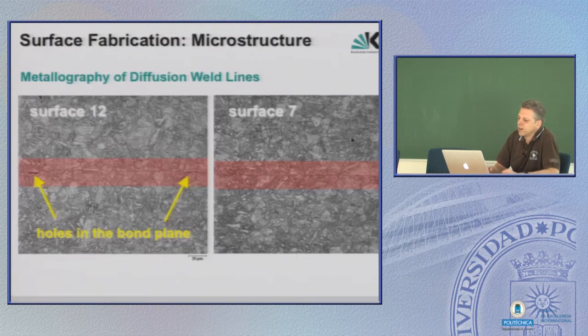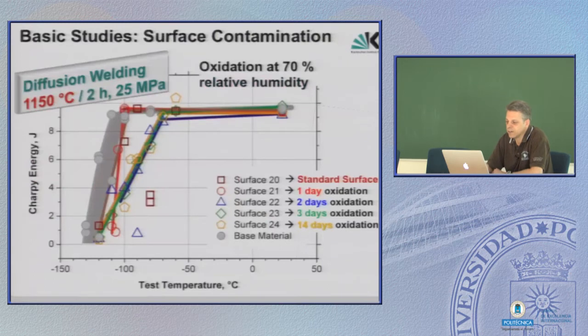In all other cases where the behavior was good, sometimes you still see a weld line, but well, it produced good results, and so first we didn't mind that you still see a weld line after the welding. With diffusion welding, you won't see anything after welding. That's the point. But okay, the result is what's counting, and so we proceed.